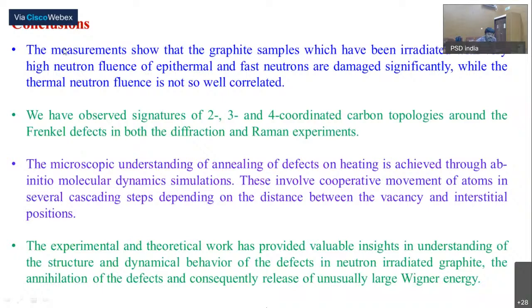So these are the conclusions. The measurement shows that graphite samples which have been irradiated with very high neutron fluence of epithermal and fast neutrons are damaged significantly, while the thermal neutron fluence is not so damaging. We have observed signatures of 2-coordinated, 3-coordinated, and 4-coordinated carbon topologies around the Frenkel defect in both the diffraction and Raman experiments. The microscopic understanding of annealing of defects on heating is achieved through ab initio molecular dynamics simulation. These involve cooperative movement of several cascading steps depending on the distance between the vacancy and interstitial positions. The experimental and theoretical work has provided valuable insight in understanding the structural and dynamical behavior of defects in neutron irradiated graphite, the annihilation of defects, and consequently the release of unusually large Wigner energy.